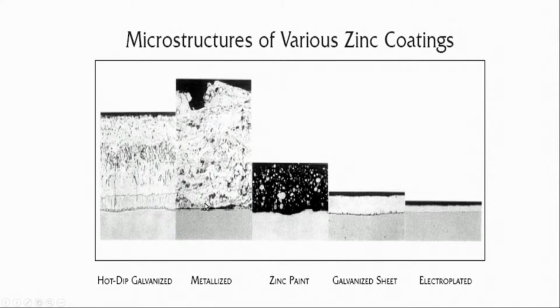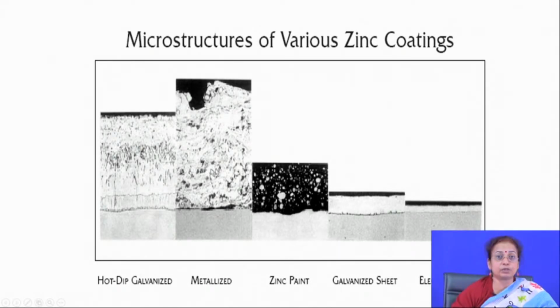At the interface there is always mechanical interlocking; there is no interdiffusion layer, and the mechanism of bonding is mechanical interlocking, and a lot of porosities and defects are there in the coated layer when you develop it by thermal spray deposition. You get a similar level of thickness, but the surface is also quite rough. Other parallel techniques are like the painting technique, where you can have zinc as dispersed particles. There, the paint layer again gives very poor interfacial bonding, and the thickness is also very low, not as high as in hot dipping, and there are a lot of defects in the paint layer.